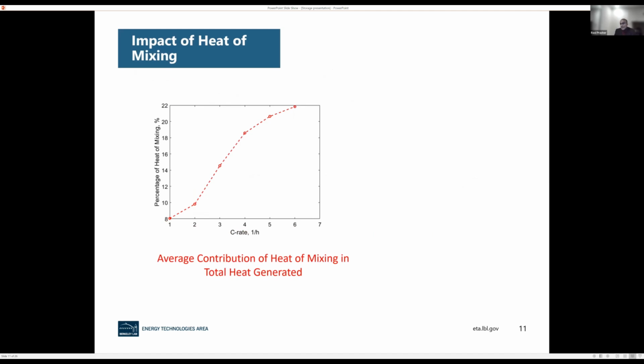So anyway, we recently calculated it, and we found out that at very high C rate or extreme fast charging that I mentioned earlier, the average contribution of heat of mixing can be as high as 20%, which is a huge number. So something to keep in mind, that heat of mixing has to be considered while you're calculating heat generation in extreme fast charging cases.